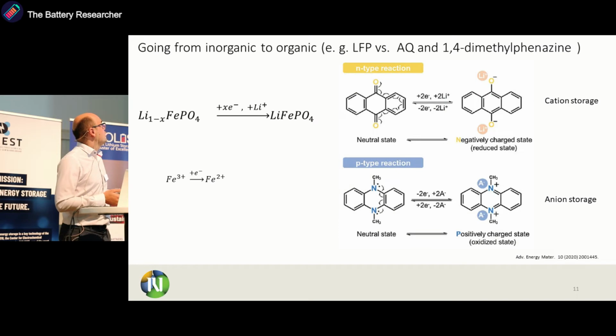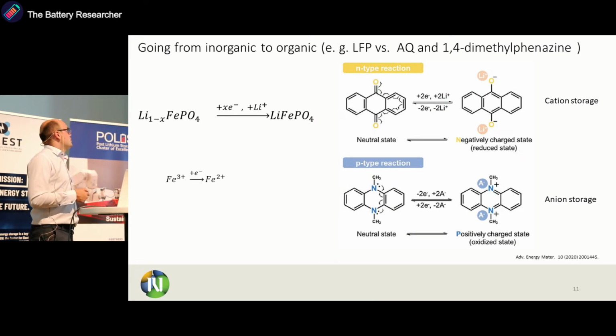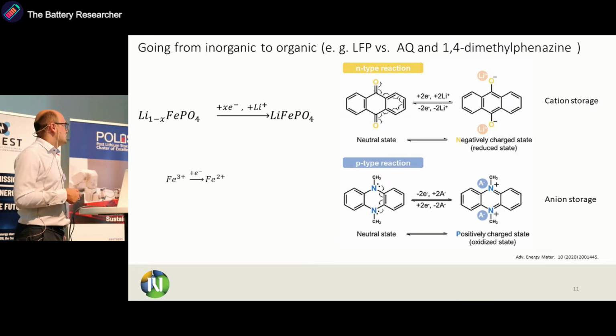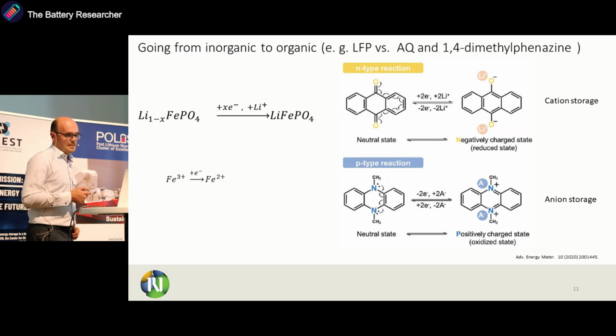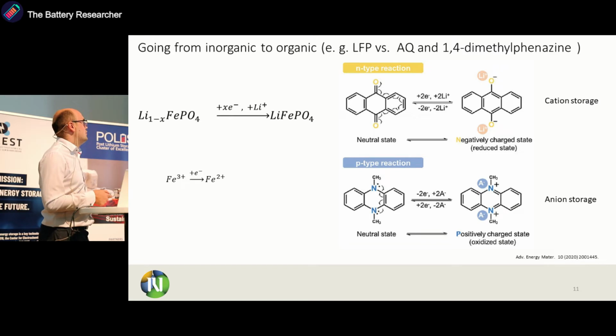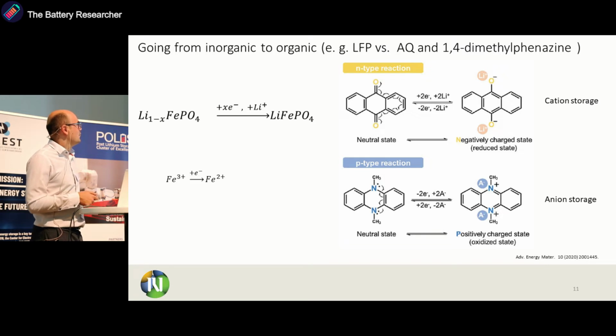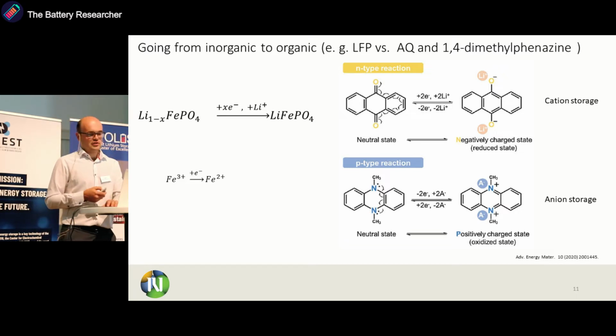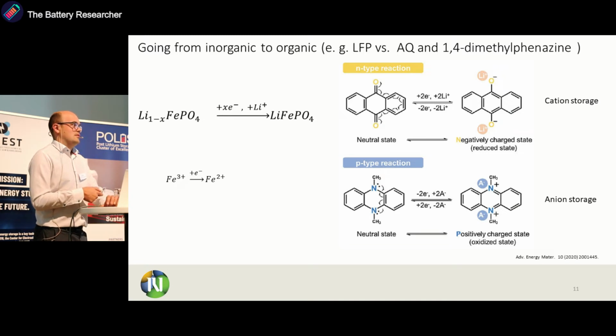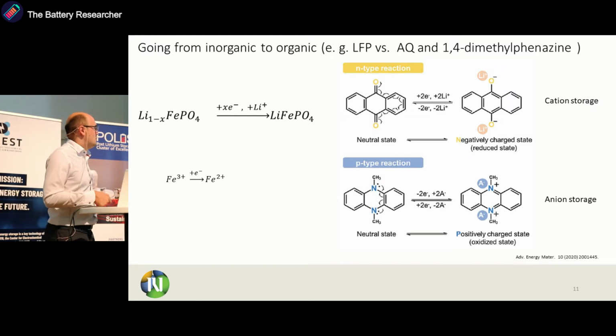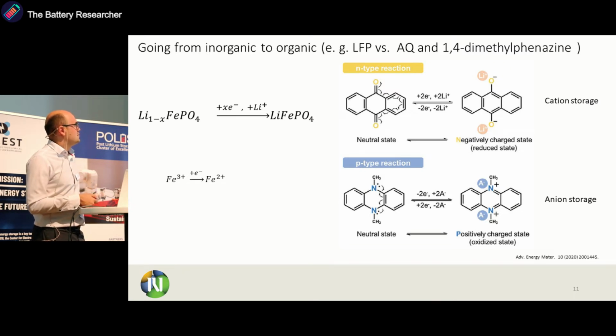We can move from inorganic to organic materials. In inorganic materials, we typically utilize oxidation and reduction of a transition metal, like here in the case of lithium iron phosphate. But in organic materials, we basically have oxidation and reduction of a redox group. And we can divide these materials basically into groups. We have N-type materials, which accept electrons and become negatively charged, and then they need a positively charged cation. And then we have P-type materials, which give away electrons and become positively charged and require an anion. This already gives us quite an important message: if we want to have operation in lean electrolyte condition and cation storage, we need N-type materials, and if we want anion storage, we need P-type materials. So basically, if we want to work with multivalent metals, we need N-type materials.